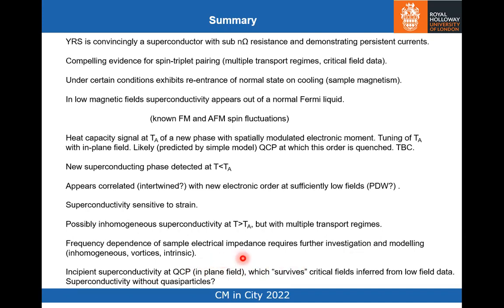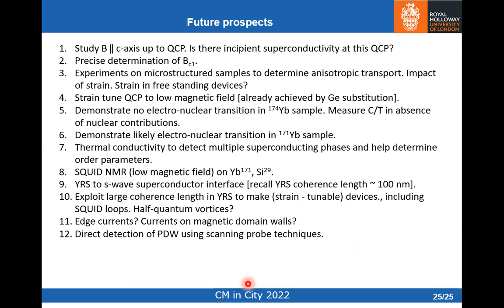And last but not least, we see incipient superconductivity at the quantum critical point for in-plane fields. This is surviving the critical fields that we're determining from the low field data. So does this have to do at all with superconductivity without quasi-particles? This is what we want to do next.